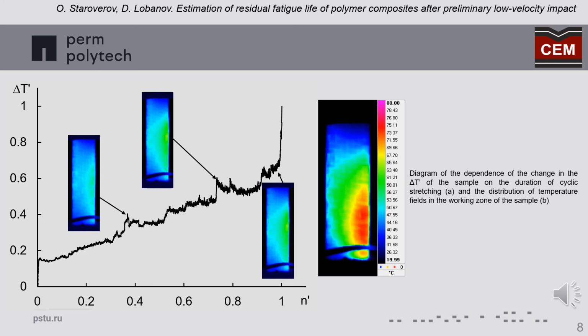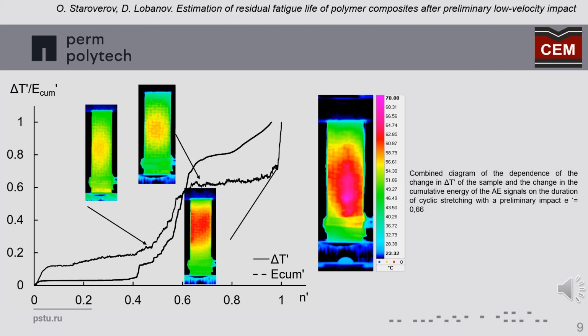The obtained experimental data are presented in the form of dependencies of the change in the relative value of the maximum temperature, delta T, of the sample on the duration of cyclic stretching. Analysis of the data obtained allows us to conclude that the curve describing the change in the value of maximum temperature is monotonic until the appearance of localized heating. At impacts with energies in the range from 0.33 to 0.66, the processes of fatigue damage accumulation occurred in several stages, which was confirmed by a qualitative agreement of these results.